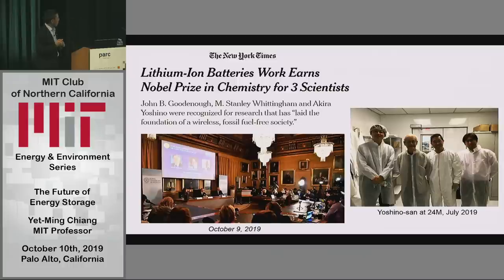Now, what Stan did back in the very early 70s at Exxon, New Jersey, was that he created a battery much like what I showed earlier, which is a lithium metal electrode against a cathode, which at that time was titanium disulfide. So that battery demonstrated that you could use lithium, and secondly, that you could use a compound called an intercalation compound as a cathode. But what didn't work was that the lithium metal electrode did not actually function well for long enough and safely enough. Exxon did not commercialize that technology. The company that did, called Moli Energy, essentially went out of business because they were the first to market with a battery that used lithium metal.